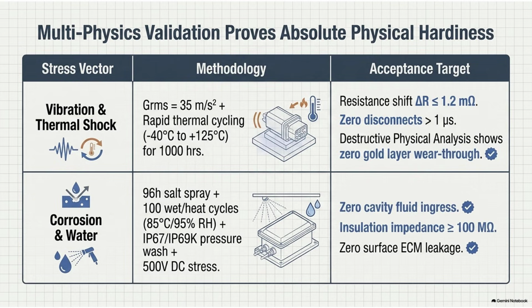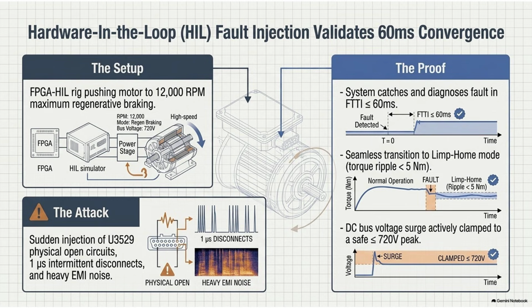They physically, visually verify that the 1.27 microns of gold plating didn't wear through to the nickel barrier, and that the phosphor-bronze substrate didn't suffer any microscopic friction oxidation or stress fracture. Oh, they demand absolute, undeniable visual proof of physical survival. Okay, so the metallurgy holds up.